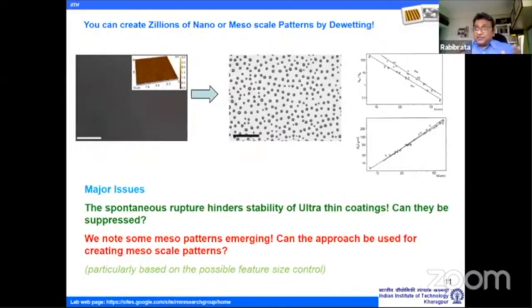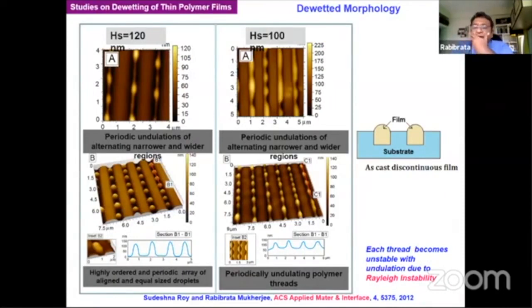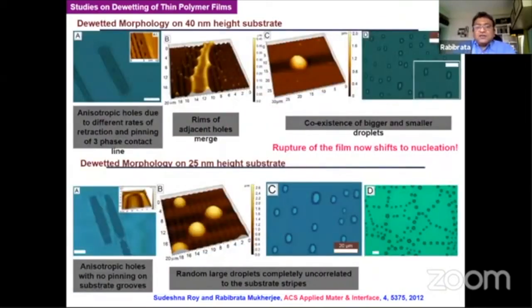So it's obvious that from the standpoint of coating, it is bad, but it is also interesting to note that you almost do nothing and you create large number of nanostructures. And I do not need to tell to this audience that nanostructures find wide application in several areas. So only problem is a spontaneous instability mediated structure is always random and isotropic. So there has been a lot of work, even we have contributed in this area for a while, of making these films dewetted on topographically patterned substrates, and then you can align these structures either in the form of aligned droplets or undulating threads and whatnot. So all type of very fancy looking structures we could create. These structures have no utility, of course, let me add as a sort of a deterrent, but nonetheless, the physics is very, very rich.